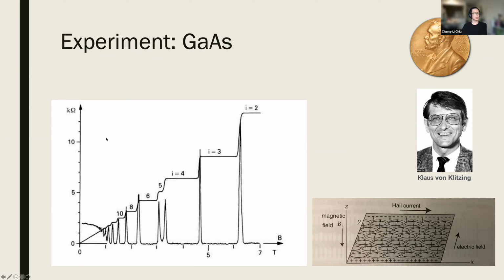And to understand this figure, we can think of a naive picture: when you apply a magnetic field, the electron moves in a cyclotron behavior, and depending on the magnitude of your magnetic field, the size of the cyclotron orbit becomes different, and that size is more like a lattice size. In your sample with finite size, you can use this to calculate how much density is needed to fill one Landau level. And if you fully fill your Landau level, you will see that the whole material becomes fully filled. And in that case, you will see a resistance